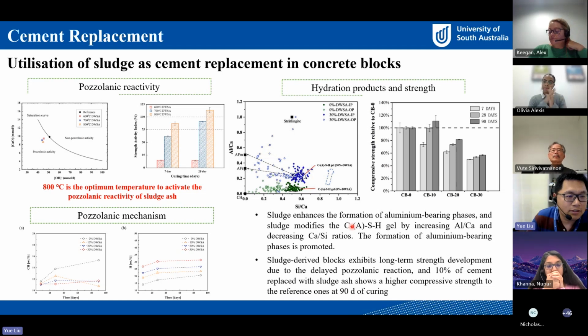In real practice, we put the sludge in to produce some concrete blocks, and we found the sludge blocks show long-term strength development due to the delayed pozzolanic reaction, and the 10% cement replaced with sludge shows a higher compressive strength than the reference one at 90 days of curing. The delayed pozzolanic reaction is because, as I said, normally the pozzolanic reaction happens when the cement hydration produces enough